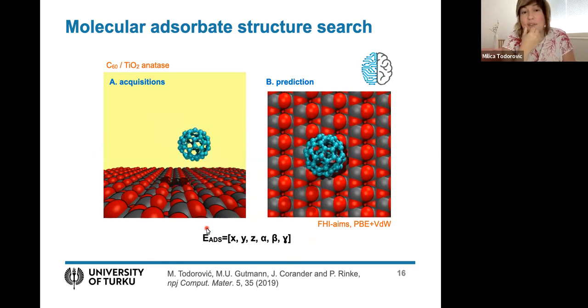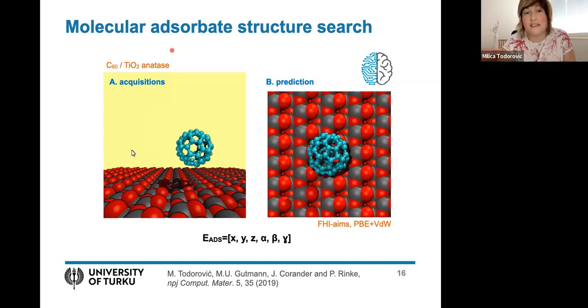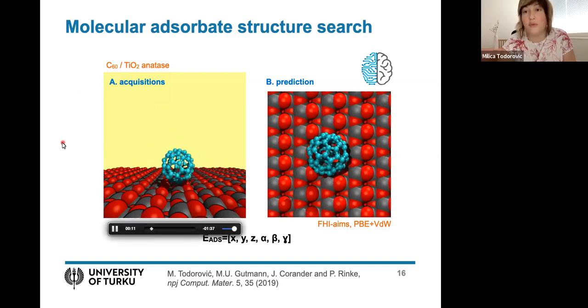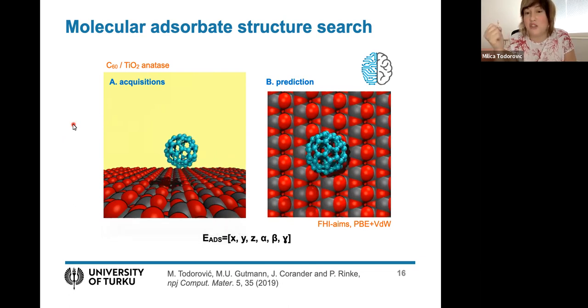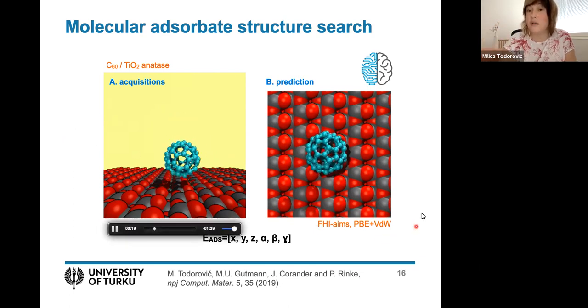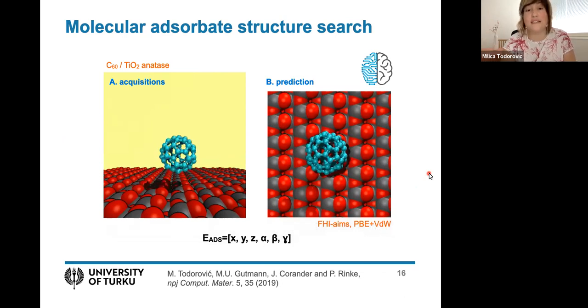And the way the active learning works is it samples in an automated way many different structures. So you can see these acquisitions on the left, that's the movie here. And then at the same time, it's building the six-dimensional model for the energetics of adsorption, and it's extracting the global minimum. And what you see here top down is the current global minimum structure as the sampling progresses. So as the sampling progresses, we know more and more about the energy landscape, and we can determine the global minimum with more accuracy.